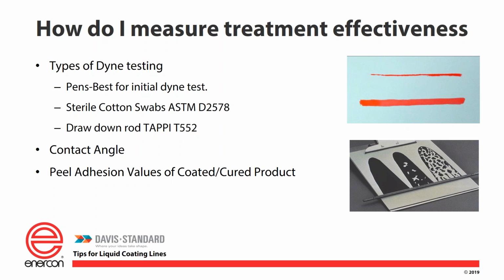where it's receding, where that dyne solution is breaking up, and it's usually on the edges of the drawdown, which is really important because as you go forward on this test method, you're looking really for consistency. How consistent are your results day after day after day when you do these tests? And in my opinion, in my years of experience, I recommend highly using a drawdown rod test method for your dyne testing.